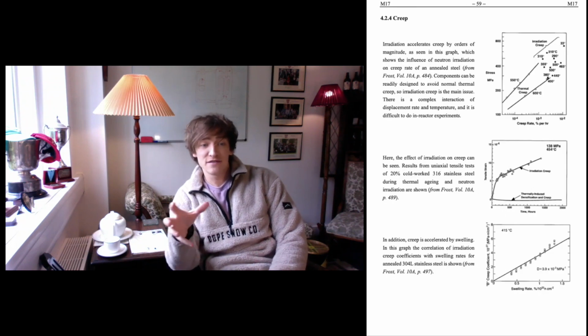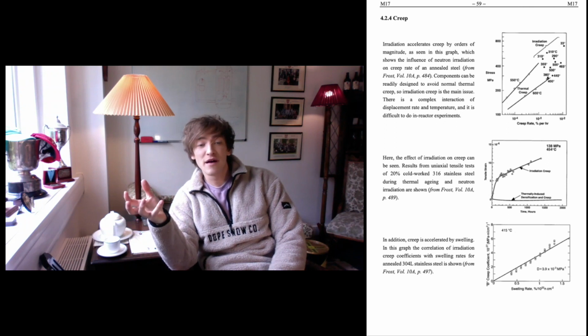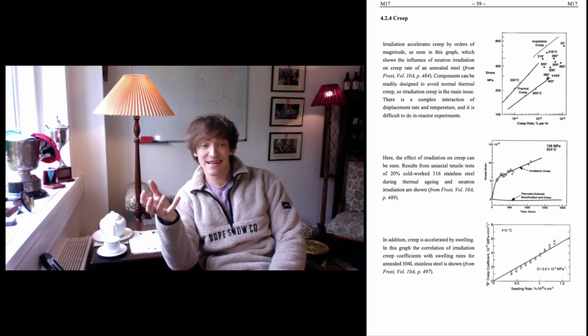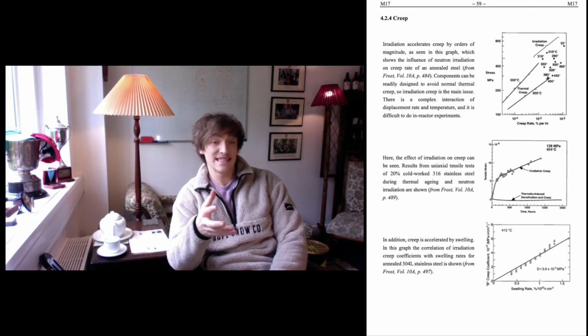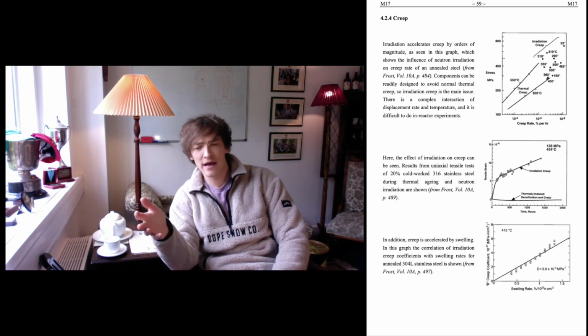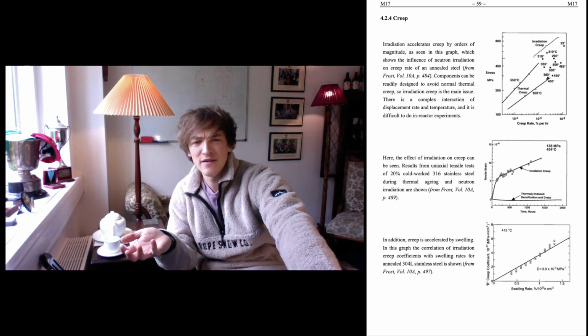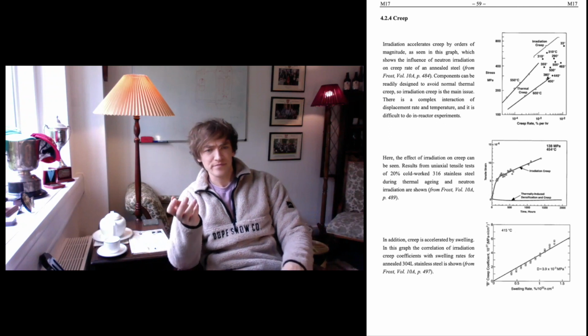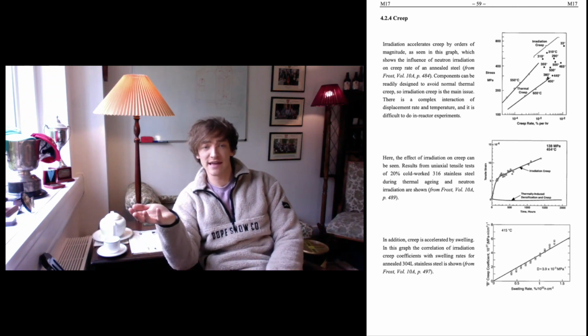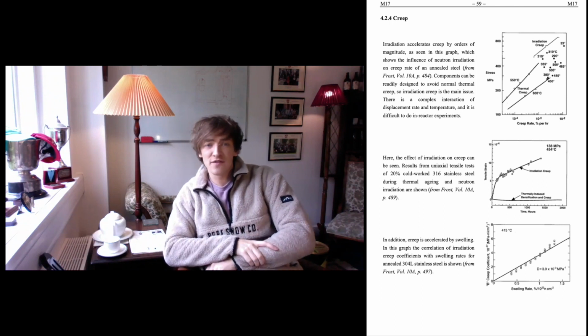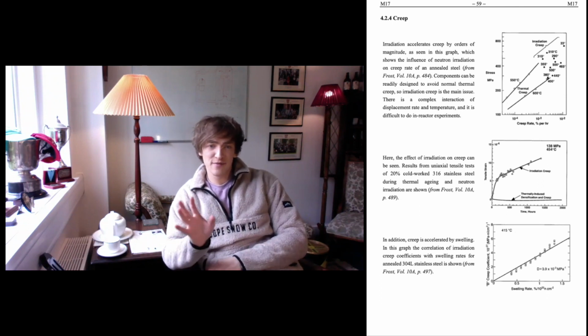Now we'll look at creep. So stainless steels for creep, we know that from our foray into fuels that irradiation can accelerate creep or initiate it at temperatures below that where we wouldn't expect thermal creep to occur. Well, the same goes for stainless steel cladding. You can get creep accelerated by orders of magnitude, which is what you see in these graphs here on page 59, which you're welcome to peruse at your will.